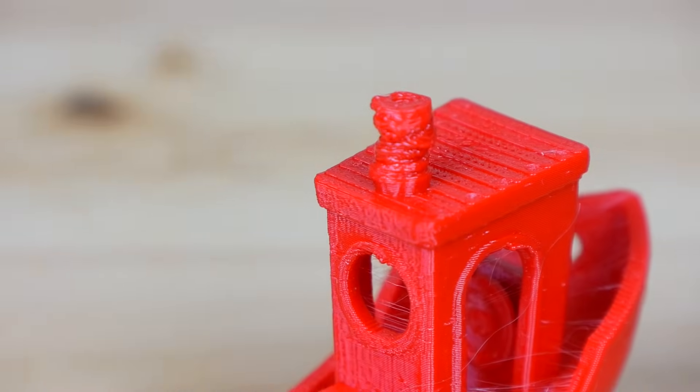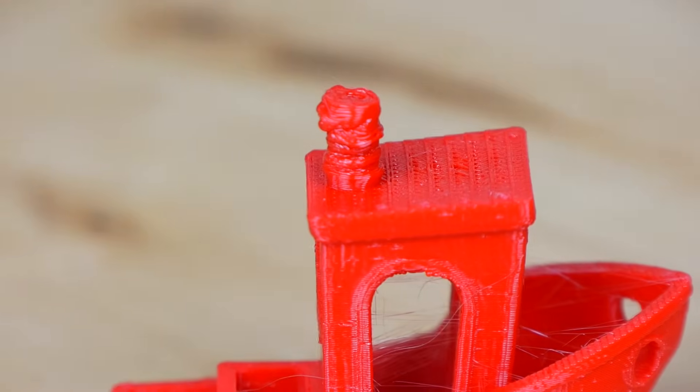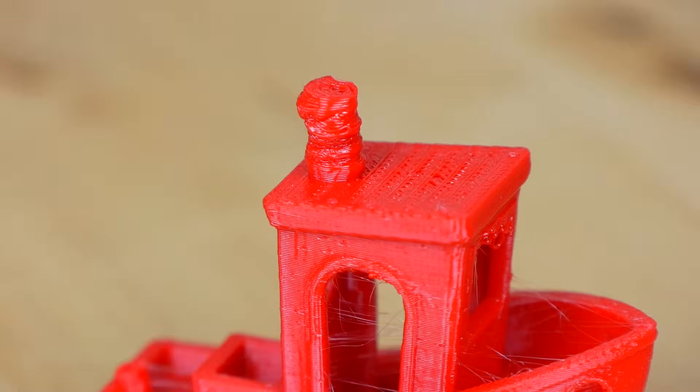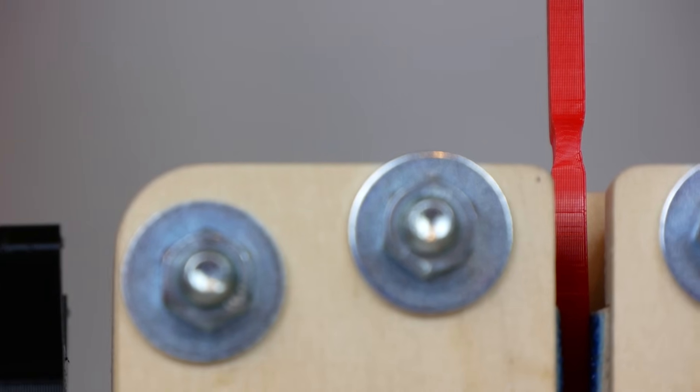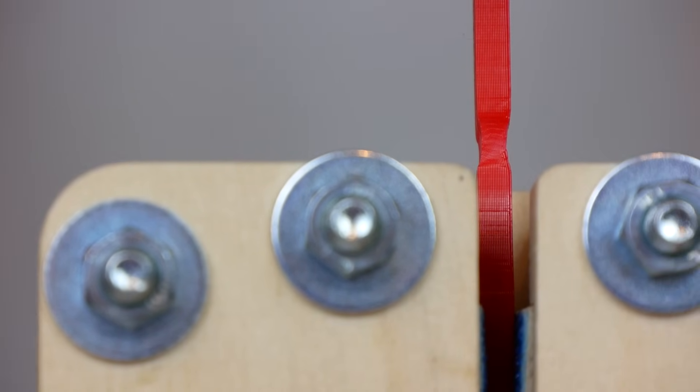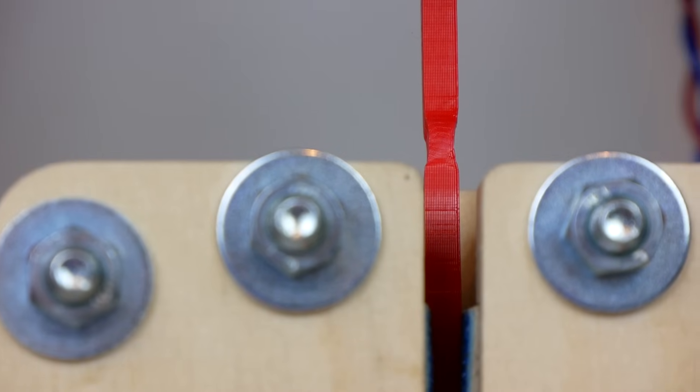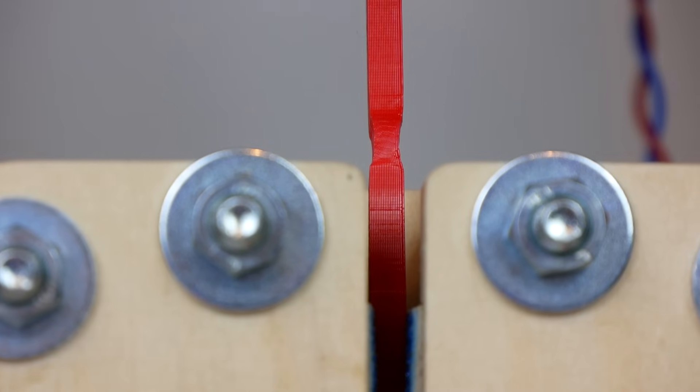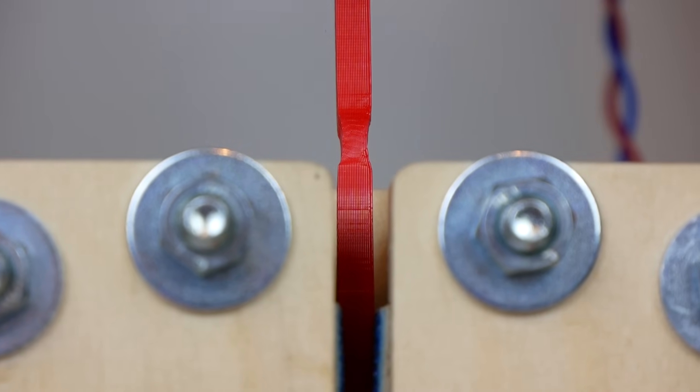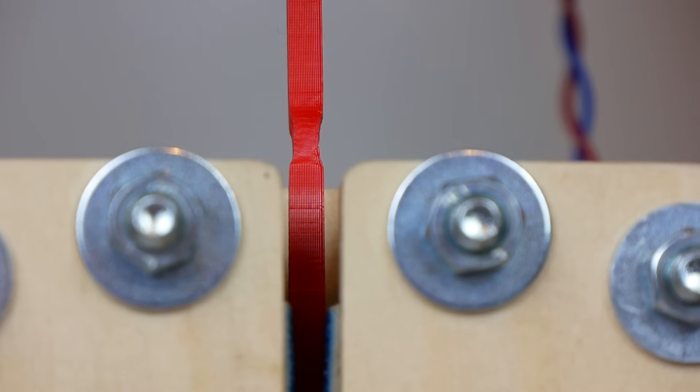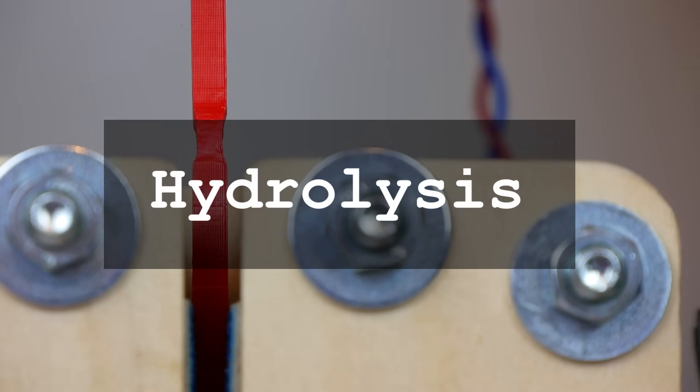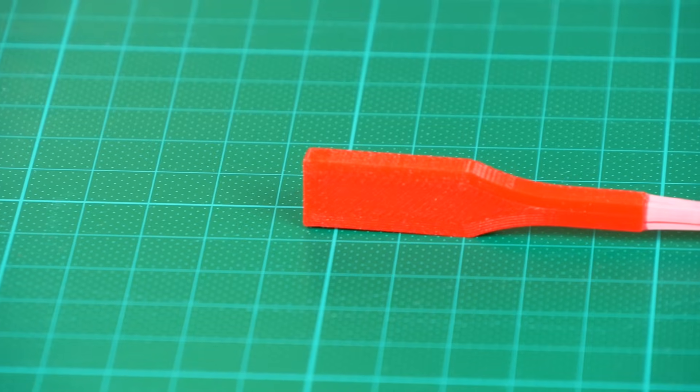I have also noticed during my tests, and this is also my general experience with PETG, that it is sometimes just inconsistent to use. I printed out one batch of specimens on a very dry day and one on a humid day. The ones printed on the humid day had significantly less strength than the ones from the dry day. This shows that the material is probably susceptible to moisture, which is a downside for this material group.